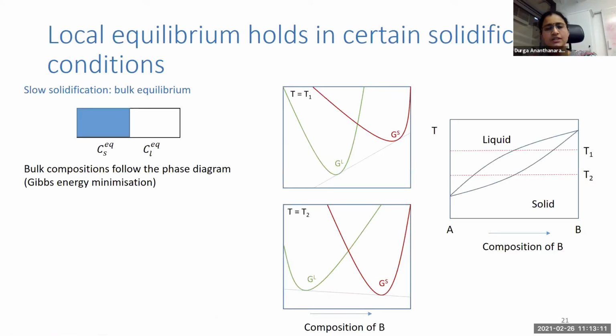Next, solidification. There's a lot of discussion on this. Is local equilibrium valid, or do we need to go to non-equilibrium effects? So first, let's start with the basics. When we have very, very slow solidification, we always have bulk equilibrium in the system. If at a certain temperature below the liquidus temperature some amount of solid has formed and there is liquid, and we want to know the compositions, then we have the Gibbs energies at that temperature, and we construct the common tangent, which gives the minimum Gibbs energy. Then we can read off the compositions, which is what the phase diagram shows. And then we go to another temperature and so on.